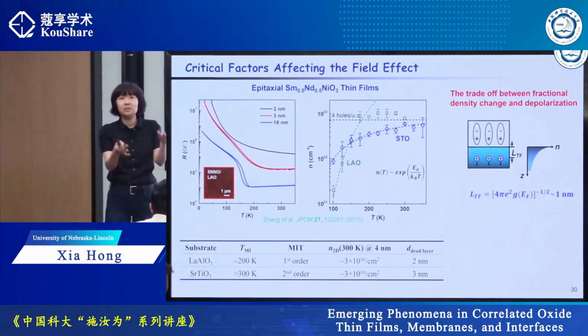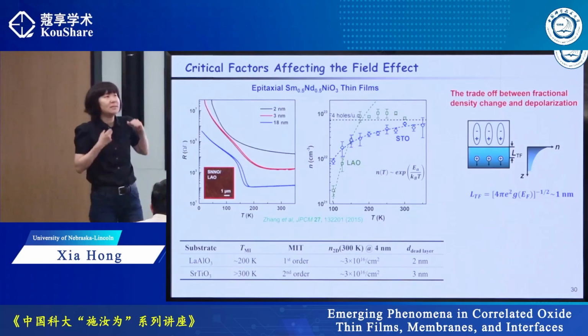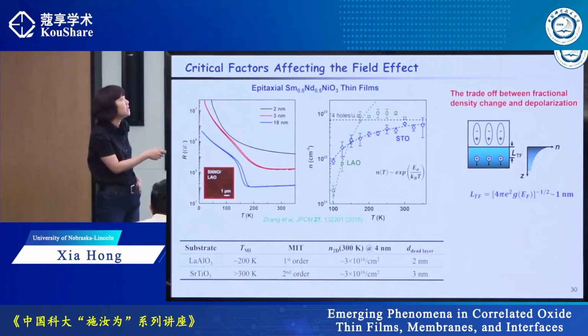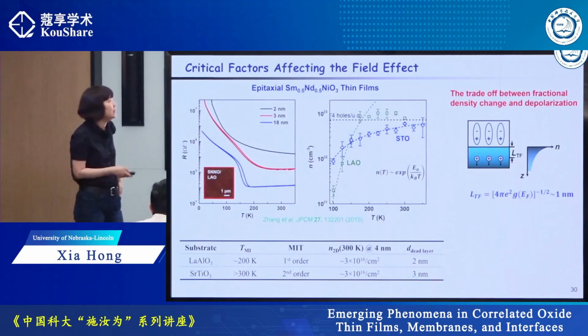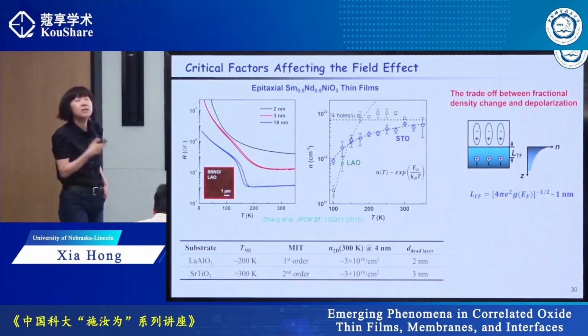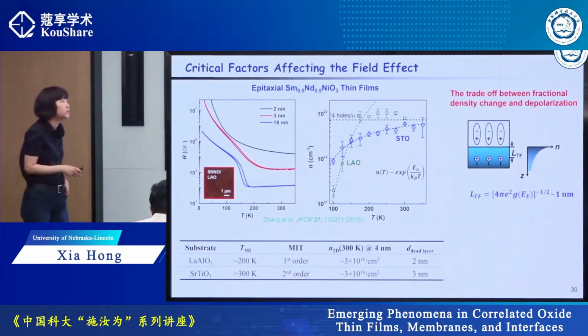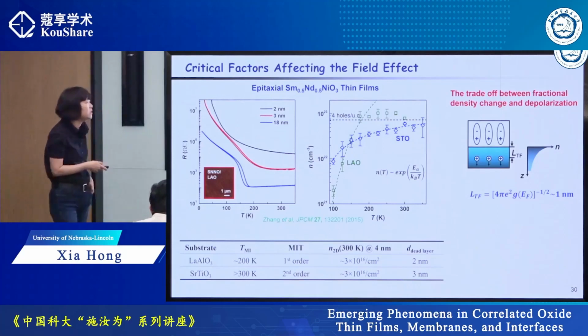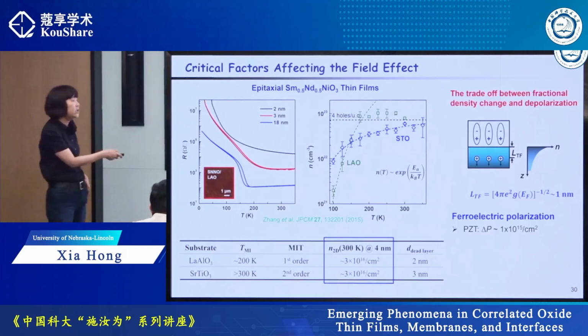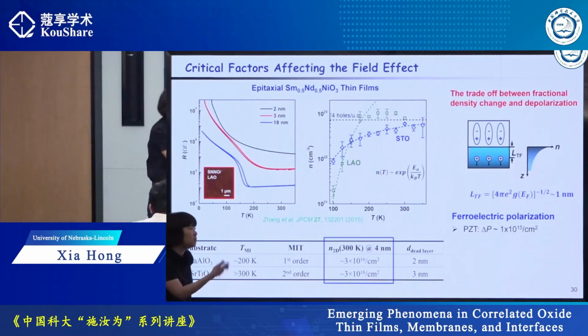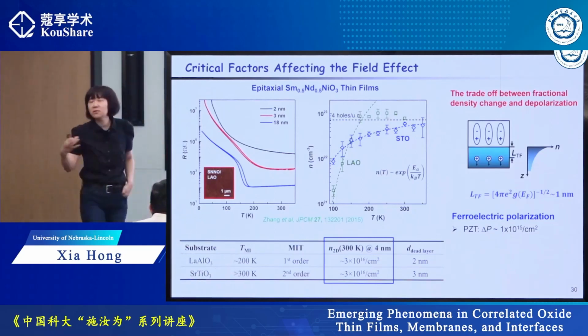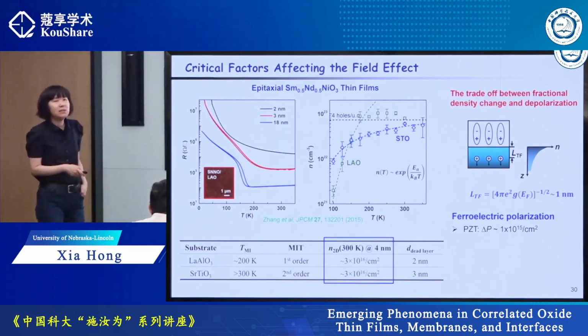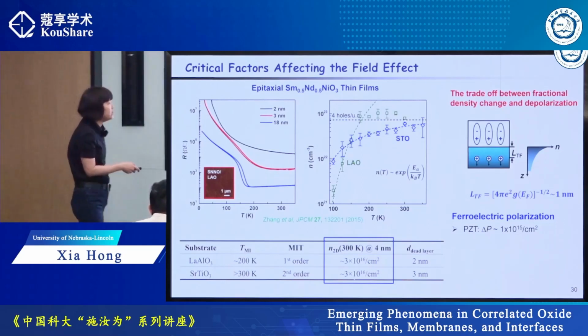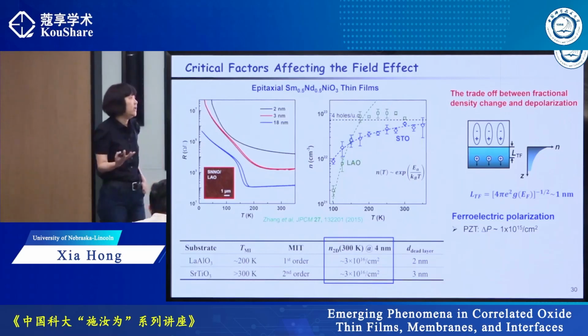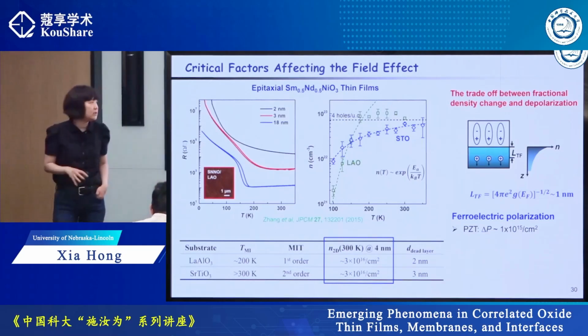The field effect is we have a parallel plate capacitor, right? And basically, the gate produces a displacement field that changes the carrier density at the interface to screen that displacement field, so it becomes continuous. So the first thing we have to consider is the carrier density. If the displacement field or polarization of a ferroelectric is only on the order of 10^15 per centimeter squared, and the intrinsic carrier density in the materials is 10^16, I can only produce 10% of change. So that's not a lot.